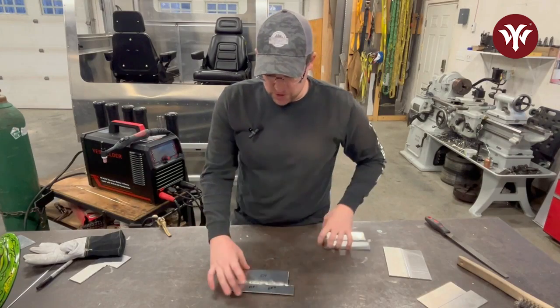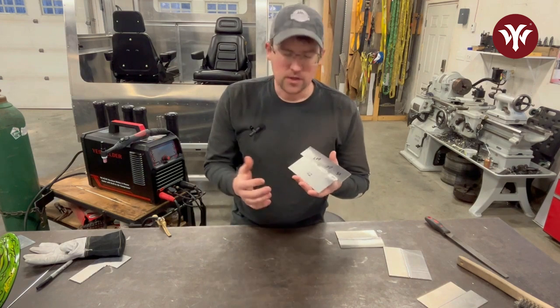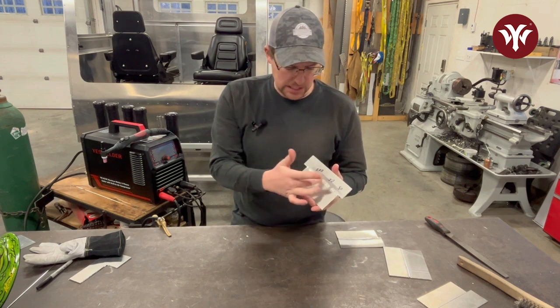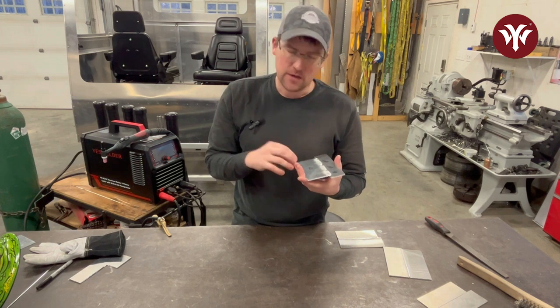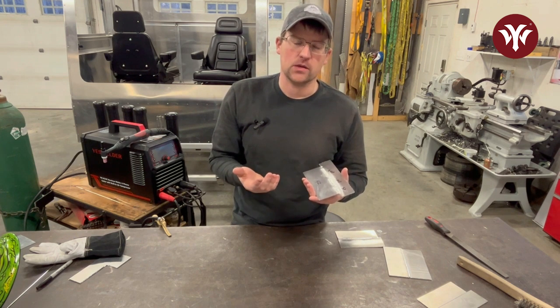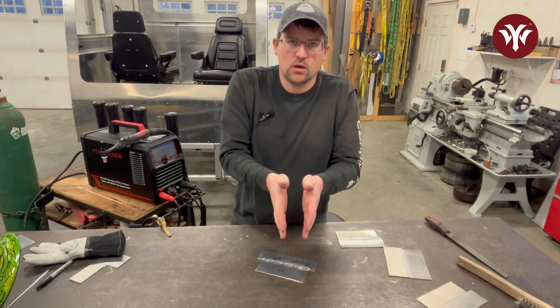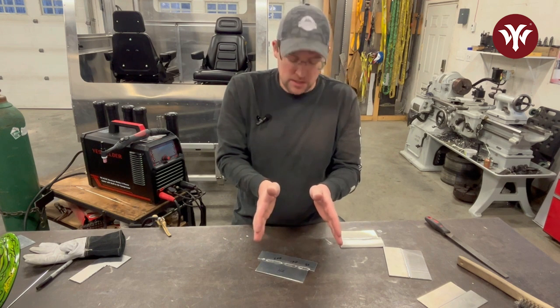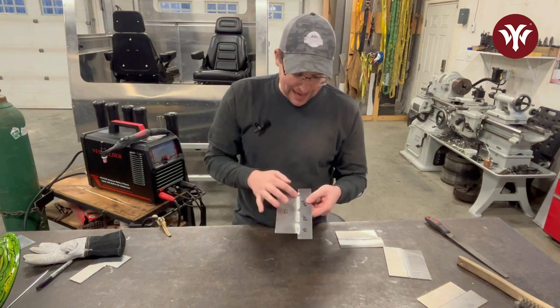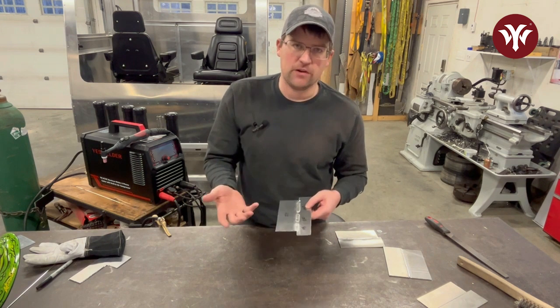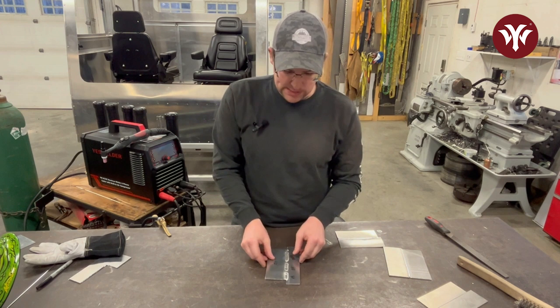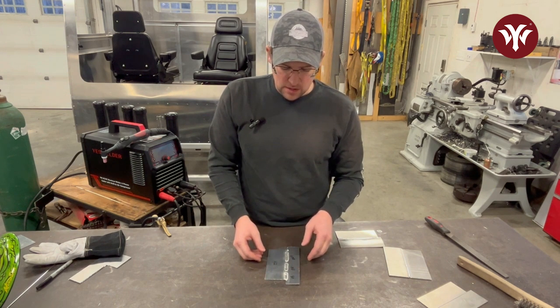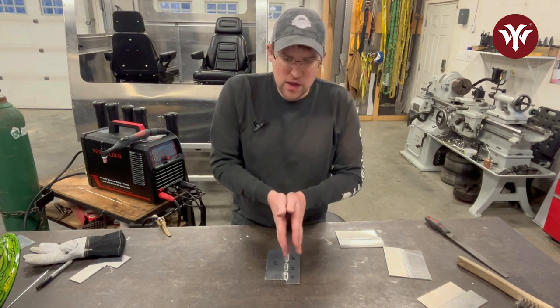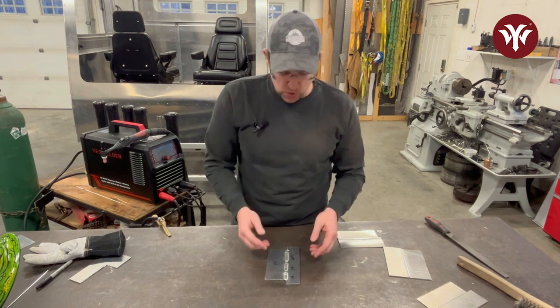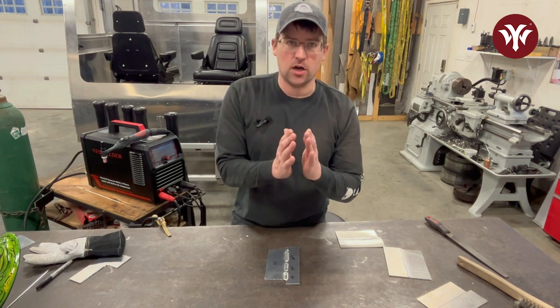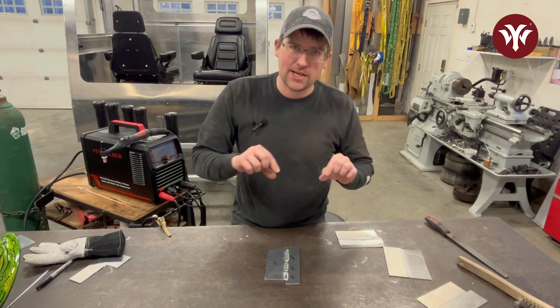All right, well, I showed you what changing the frequency did there. Really, you can hear the difference between 50, 100, and 200 Hertz. If you do any research on adjusting the frequency when AC TIG welding, it really has to do with adjusting your arc and the width of your puddle and everything like that. I didn't see a ton of that happen here, but that is what frequency adjustment is for. A lower frequency like 50 Hertz is going to create more heat into your part. The arc widens out. And as you go to higher frequency, it's gonna really tighten that arc up, bring it much into a tighter bead.